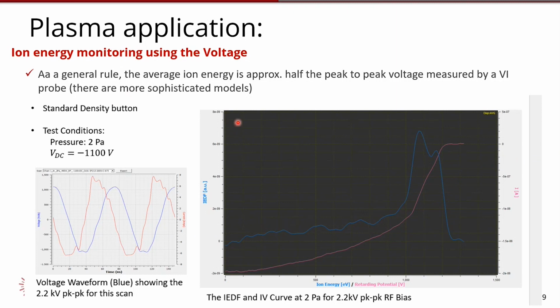So certainly in low pressure conditions, approximately half the peak-to-peak voltage you measure will tell you what your average ion energy is. There are more sophisticated models than that, of course, but as a very simple application, that's a quick way of getting good results. This data here is from a VI probe. The blue line is the voltage waveform, and the red line is the current waveform.